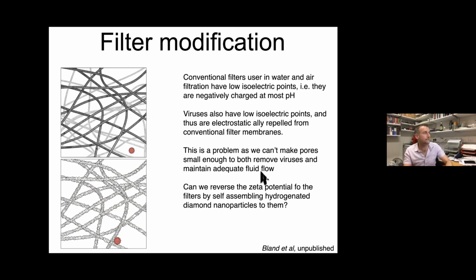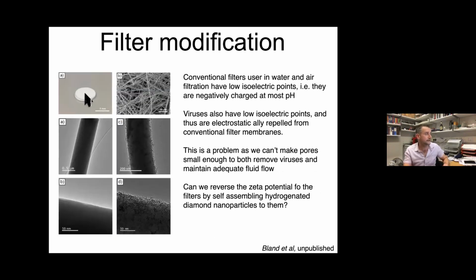So what we did is we took a quartz membrane. So here's a quartz filter, right? Standard quartz here, and this is what it looks like under the microscope. You can see that the pores in this membrane are really, really big, right? The virus will go straight through here. We've tried it. It's not good. This is what they look like under the TEM, and this is what they look like when we coat them. So we coat them and then we do a reaction. I can't say what it is because we haven't submitted this yet, but it's pretty obvious.